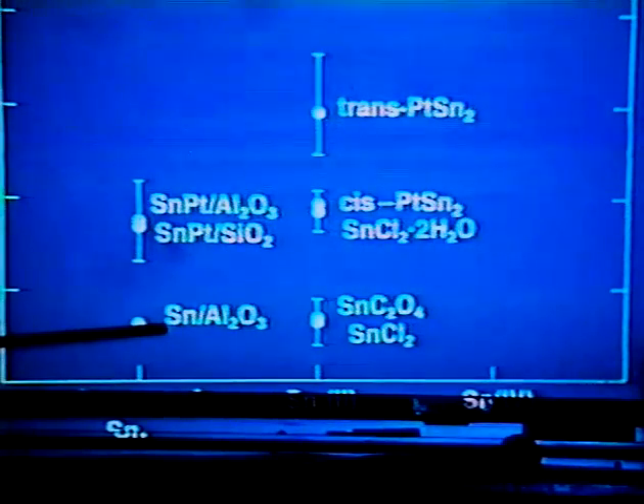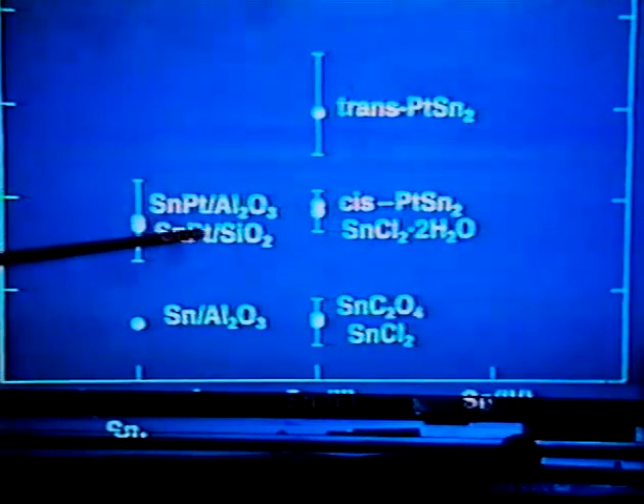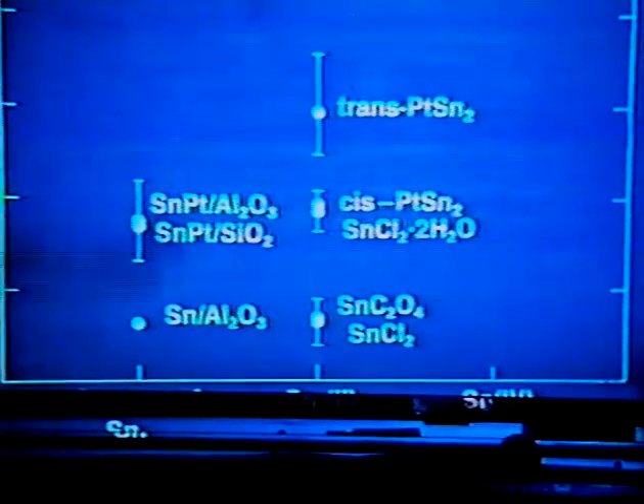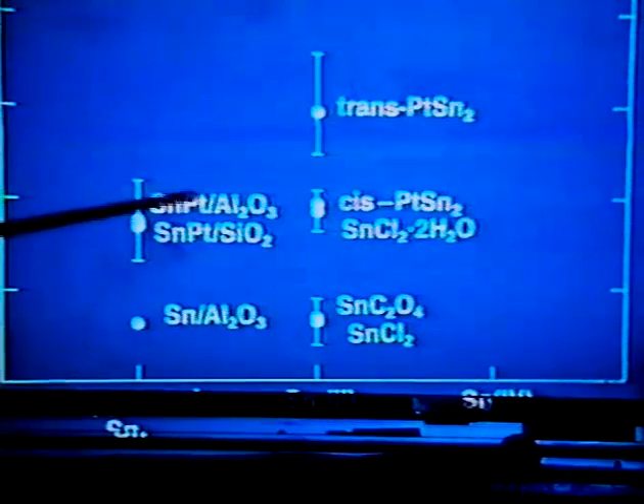The conclusion then is that in these catalysts, the binding energy of the tin is either comparable to that of tin-0 or tin-2, but this is definitely not tin-4 in the catalysts. Now what we've seen is that tin on silica with platinum has a metallic environment, so we say it's tin metal, and it's formed intermetallics. Tin on alumina has a lot of oxygen in its environment, so we say it's probably tin-2. The tin with platinum on alumina has a short platinum-tin bond as well, so we say there's probably an anchoring site, which is a sort of bonding interaction between platinum and tin on those supports, on alumina. Next slide.